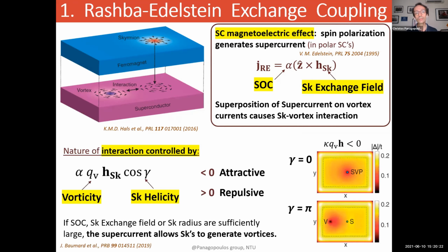Now, the nature of this interaction would be controlled by the vorticity and the skyrmion helicity. If this is negative, that would be an attractive interaction. If it is positive, it would be a repulsive interaction. So if spin-orbit coupling, skyrmion exchange field, or the skyrmion radius are sufficiently large, then the supercurrent would allow skyrmions to generate Abrikosov vortices.